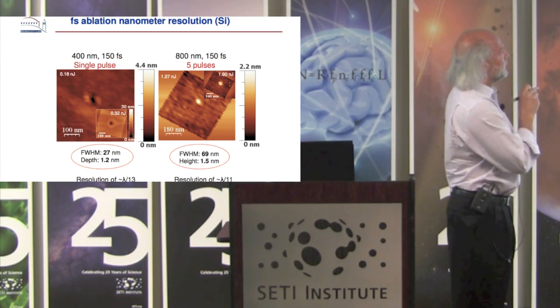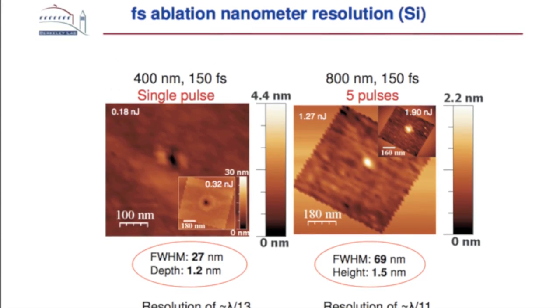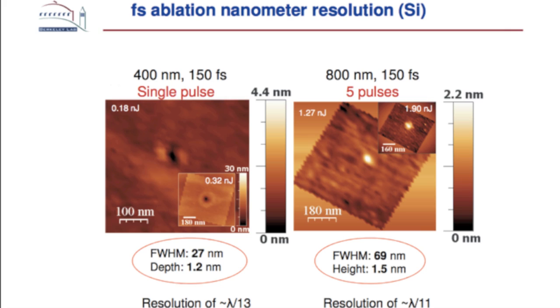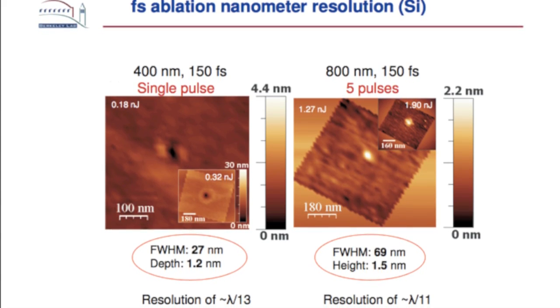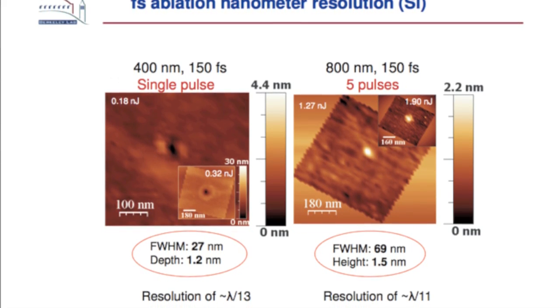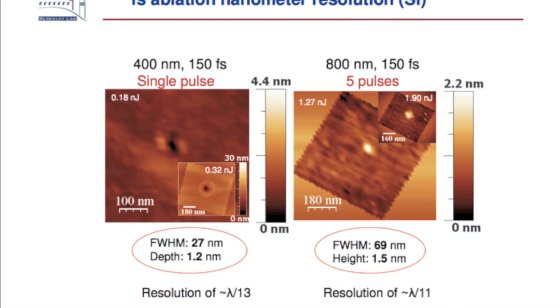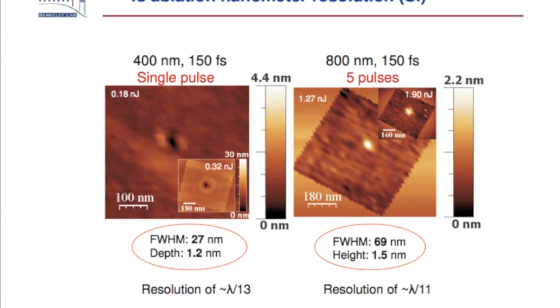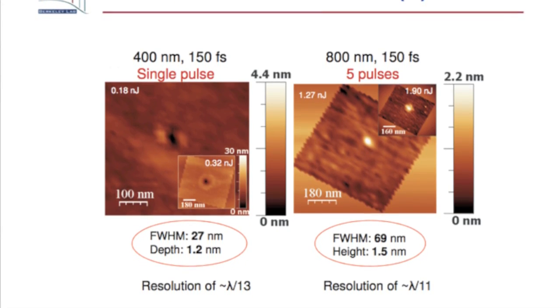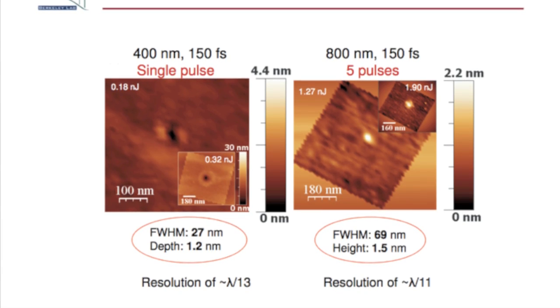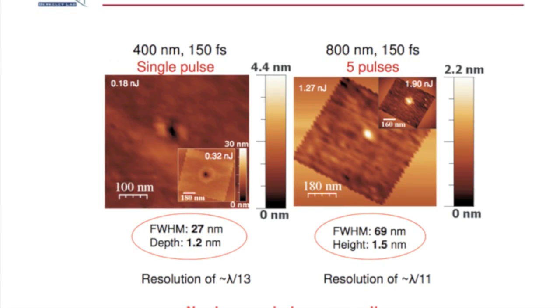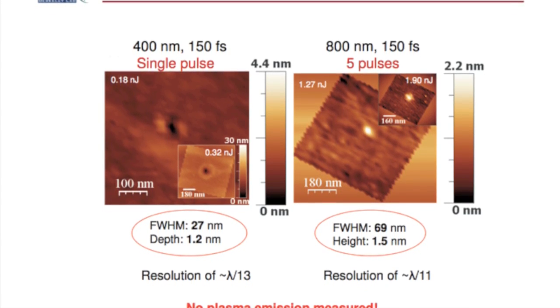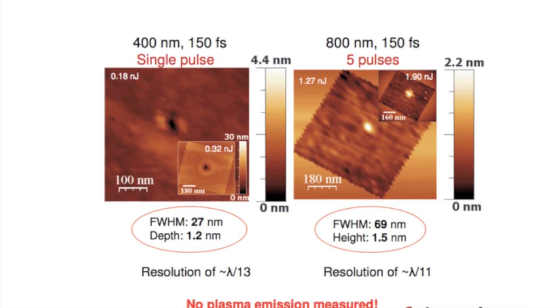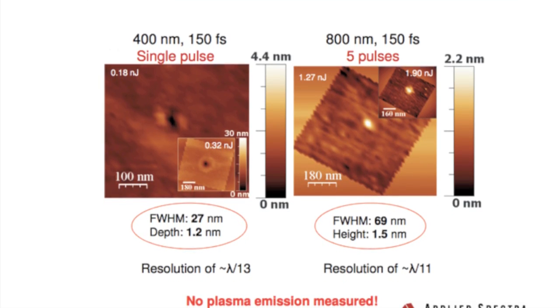So the best we've been able to do is using a femtosecond laser with an NSOM, a near field scanning optical microscope. So it's a commercial system. You basically can buy different fibers. It has all the piezoelectrics for telling you where you are with respect to your sample. We can actually make craters now. We can do laser ablation down to a diameter of about 27 nanometers and a depth of about 1.2 nanometers if we're using the 400 nanometer, 150 femtosecond pulse.